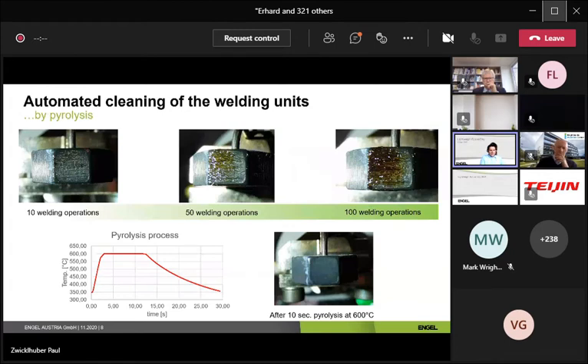During the processing, a thin layer of thermoplastic material can build up at the tip of the welding stamp over time. The degree of accumulation depends strongly on the type of polymer. This layer can have a negative effect on the spot welding process. The three pictures at the top show the tip after 10, 50 and 100 welding operations.